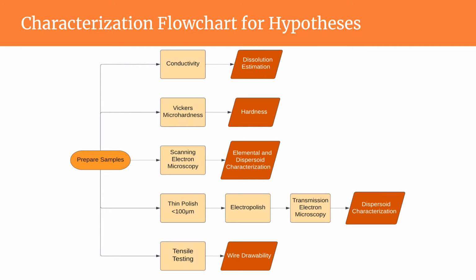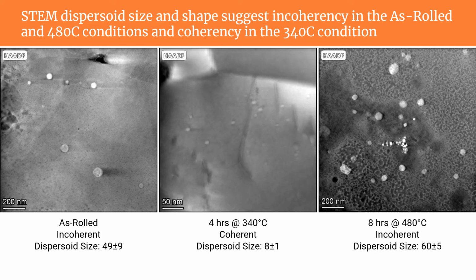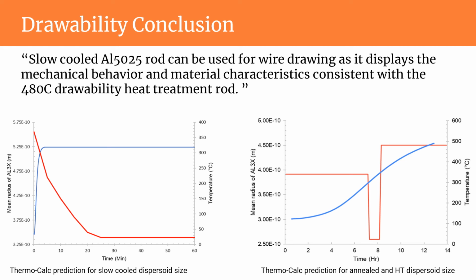In order to identify the best thermal process to allow for drawability, mechanical, conductive, and microstructure characteristics of peak-aged and overaged Al5025 rod had to be quantified. Thermal treatments for both conditions were known from previous Hobart wire drawings. Tensile testing and Vickers microhardness were used to identify the relevant mechanical properties, while a 4-point probe was used to measure rod conductivity, and scanning electron microscopy allowed for dispersoid identification. The most intensive part of our solution was measuring dispersoid size of the samples at a nanometer scale using transmission electron microscopy.